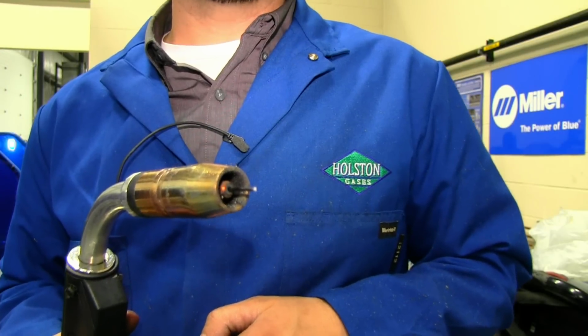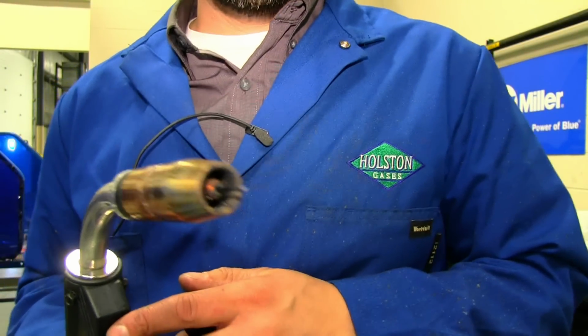Now it's critical to use the correct electrical stick out, because this stick out helps preheat the wire before it gets in the puddle. And this helps burn off any drawing lubricants or moisture that's accumulated on the wire. If this isn't done, then porosity can occur. And the type of porosity that you're likely to see is elongated porosity, which is also known as piping or worm tracking.